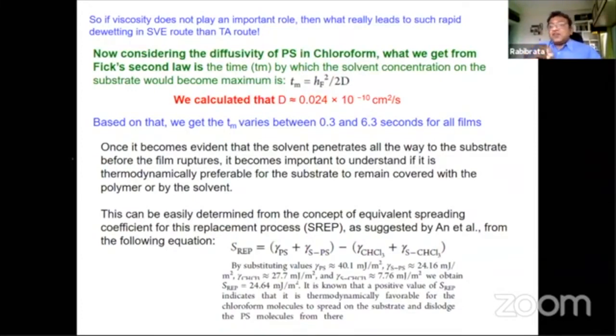So once we realized that the solvent vapor was reaching the substrate, then there was a question. What happens once the solvent molecules reach the substrate? Does it spread over the substrate on its own, or doesn't it? Or what remains, or what happens? So then we figured out there is a concept of replacement spreading coefficient, which actually looks into the spreading coefficient of the present polymer versus if the polymer is replaced with the solvent. And we figured out that if we have a replacement spreading coefficient as a positive value, then it indicates that the solvent will actually spread on the substrate. And in fact, it turns out if you calculate, the SREP is positive.